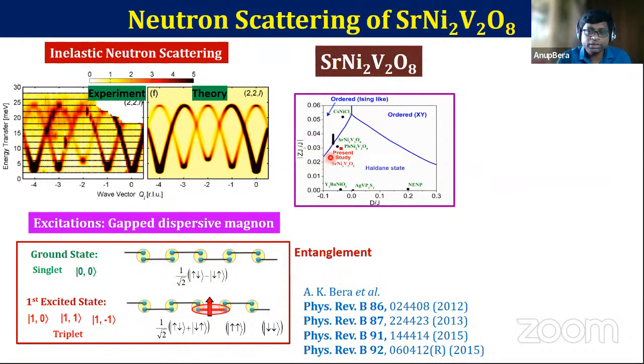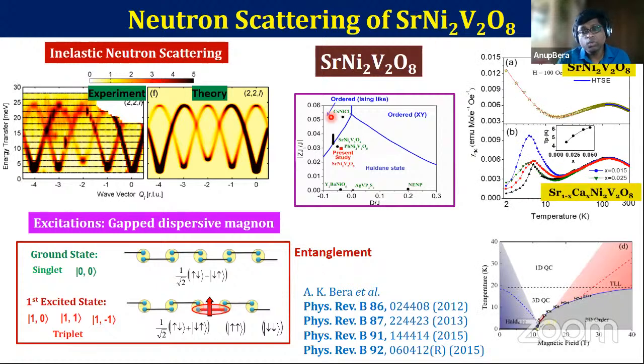Now you can see that if we increase the interchain coupling, one can drive this system from this Haldane state to the ordered state. We have shown two ways that we can drive this system to the ordered state. One is already shown by Professor Yusuf: if we dope calcium, which has a smaller ionic radius than strontium, we can bring the chains closer to each other.